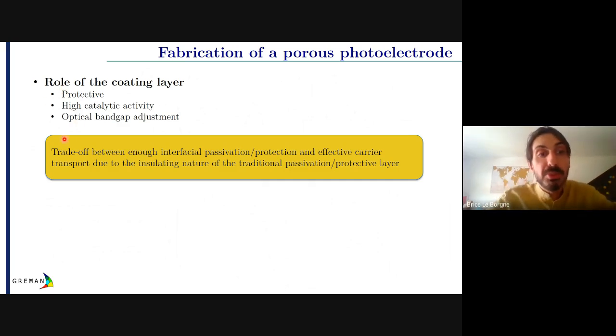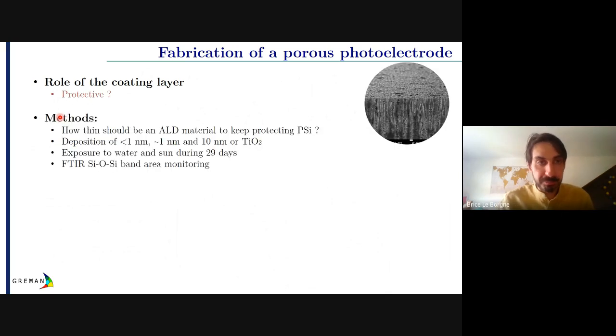So the challenge is to find the good trade-off between the passivation, the protection of the porous silicon, but keeping the charge transport for the good generation of electron-hole pairs. So the method we have, initially we're gonna check if it's actually protective. The question we ask is how thin the ALD material can be to keep protecting the porous silicon. So we deposited less than 1 nanometer of titanium dioxide, which is a good photocatalyst. It's known for that. Then around 1 nanometer and around 10 nanometers.